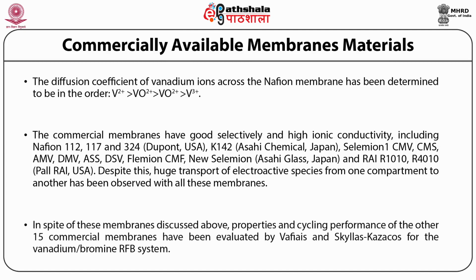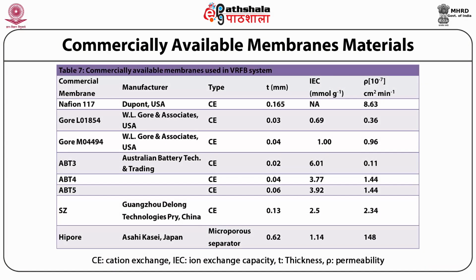In addition to the membranes discussed above, the properties and cycling performance of 15 other commercial membranes have been evaluated by Vafiais and Skyllas-Kazacos for the vanadium bromine RFB system. As observed from the table, the properties of these membranes are compared with the properties of the Nafion membrane from the literature. Although Nafion 117 and Hipore are thicker than the others, they have smaller area resistance and larger permeation of V4+ ions has been observed.